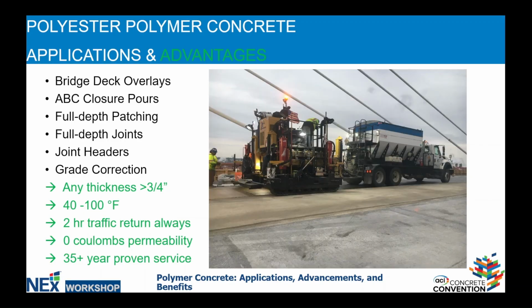So applications and advantages of PPC include bridge deck overlays, accelerated bridge construction closure pours, full depth patching, full depth joints, joint headers, and grade correction. The nice thing about these products is that they are fast. They can be adjusted, as I mentioned, based on the substrate temperature condition, with the ability to adjust the formulation in the field by playing around a little bit with the accelerator dose in the mix.